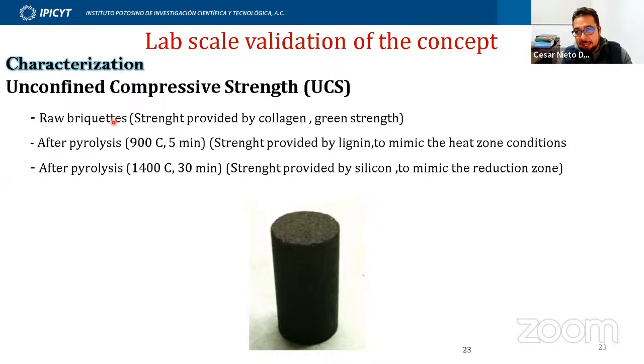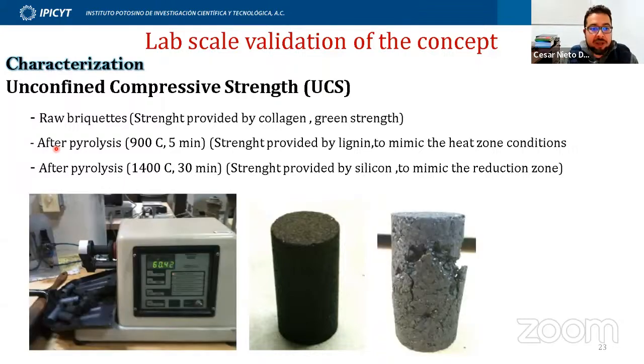We did it on raw briquettes that we only make and let dry at room temperature. And we also did it after pyrolysis at 900 to mimic the conditions in the heat zone of the cupola furnace. And then we did a pyrolysis of the briquette at 1400 C, just to mimic the conditions in the reduction zone of the cupola furnace. In that way, we validate that at very high temperature, the briquette will stand together, and also is going to have very high strength.